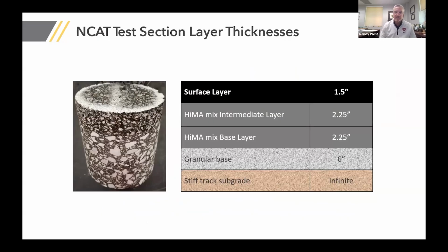On the test track, we built 7 test sections, and the experimental layer was only the surface layer, the top 1.5 inches. And we wanted top-down cracking, and we wanted to avoid having bottom-up cracking. So we used a structure with a highly modified asphalt mixture in the intermediate and base layers to be very strain tolerant, so that we would not get bottom-up fatigue cracking. And then we created the 7 mixes in this experiment with a range of mix expected performance in terms of top-down cracking. And we achieved that by just putting in some things in the mixes like polymers or shingles to create different cracking susceptibilities.